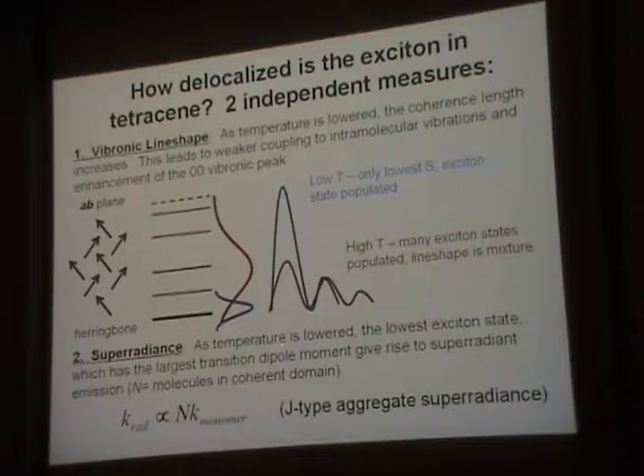The second thing is, as you condense into that state, your radiative strength is going to go up, right? Again, these guys not only have different vibronic line shapes, they also have different transition dipole moments. And so you're going to get a mixture of transition dipole moments up here, but down here you're going to get the strongest, it turns out, because of the geometry of the packing. This is what's called a J-type aggregate. Because of that geometry, it turns out that most of the oscillator strength, most of the transition dipole moment is sitting in that lowest K=0 state.